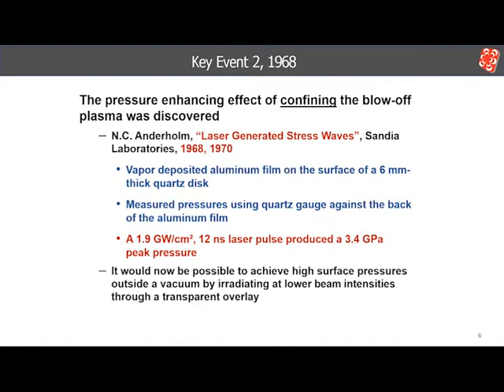The second key event occurred in 1968. Anderholm at Sandia Laboratories was also investigating some aspects of this vapor impulse, and like all the others, the target was in a vacuum because of the high laser pulse intensities used to increase the pressures and to simplify the measurement of the impulse. Anderholm made the connection that if the vapor was confined against the surface instead of blowing off, it would greatly enhance the shock wave pressure.